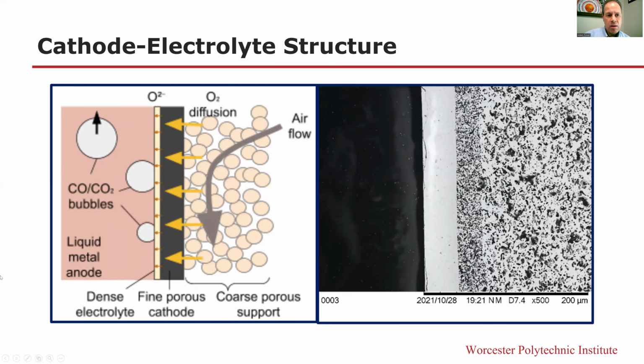Looking at more detail, as mentioned, the carbon comes through the liquid metal anode, diffuses through, it reacts with oxide ions that come through the electrolyte here to form CO and CO2 bubbles that rise and stir the liquid metal to bring more carbon to the electrolyte in the anode. On the cathode side, we have air flowing through a porous support, then diffuses through the finely porous cathode and reacts, absorbing electrons to form these O2 minus ions, and then transfer through and react to form CO and CO2 bubbles, giving up their electrons on the other side. So we can capture the electrical energy across that